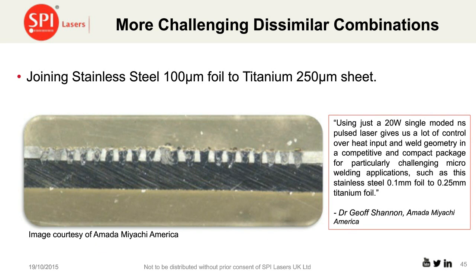In actual fact, we've found that there are some very exotic and more challenging joints that can be made. And here I have to thank my good colleague and friend, Dr. Geoff Shannon of Amada Miyachi, who let me use this picture where they've used one of our 20-watt single-mode lasers to join 100-micron foil stainless steel to titanium. Now, I'm not quite sure why you'd want to join stainless steel to titanium, but I suspect metallurgically it must be quite a challenge. And his statement here is that the flexibility that these laser sources give him enables him to make such joints.